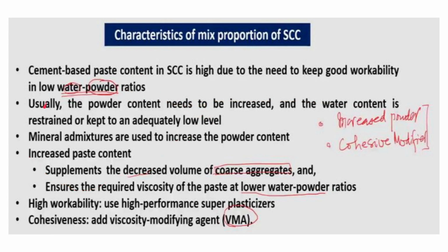Other than that, usually the powder content needs to be increased, and the water content is restrained or kept to an adequately low level. Because the aggregate is reduced, we have to fill it by powder and fine material, and because of that there is increased powder content, and the water content is restrained using super plasticizers. So mineral admixtures are used to increase the powder content. As we have studied in previous classes, water content is taken care of by using super plasticizers, and powder content is taken care of by using mineral admixtures. Okay, powder or cement content.